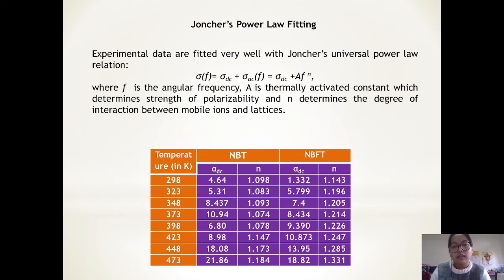Also, we can see that n increases with increase in temperature. This implies that the conduction mechanism in the samples was due to the non-overlapping small polaron tunneling mechanism.